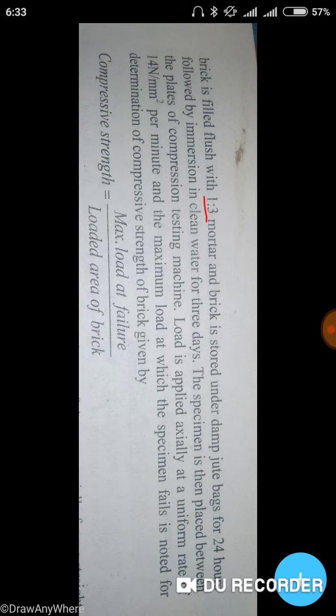of compression testing machine. The load is then applied axially at uniform rate of 14 Newton per mm square per minute. And the maximum load at which specimen fails is noted and determines the compressive strength of the brick, given by maximum load at failure upon loaded area of the brick.